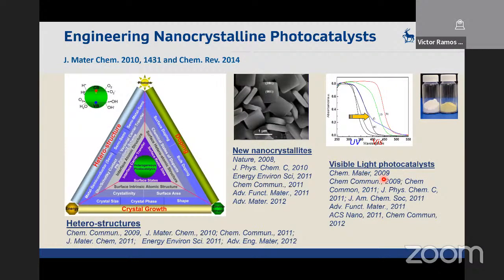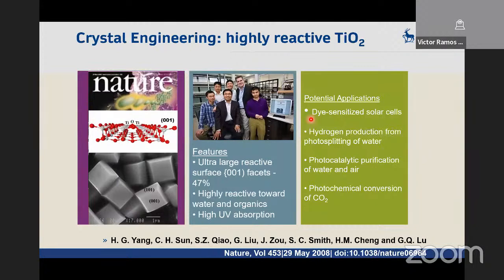So in terms of the engineering of a nanocrystalline photocatalyst, we can use heterostructure techniques, doping techniques and crystal growth techniques. They respectively control the interface carrier transfer through heterostructure, and the doping will eventually modify the surface redox sites. And then the crystal growth will eventually improve the surface state conducive for the different applications. And we have done many projects in those three domains, trying to optimize the electronic structure, the crystal structure, and the surface structure of a photocatalyst.